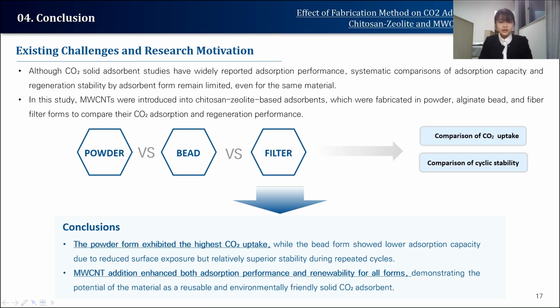This study leads to three main conclusions. First, the fabrication form significantly affected CO2 adsorption performance. Second, adding MWCNT improves both adsorption performance and regeneration behavior. Third, when practical use is considered, the bead-type composites containing MWCNT appear to be the most favorable design.